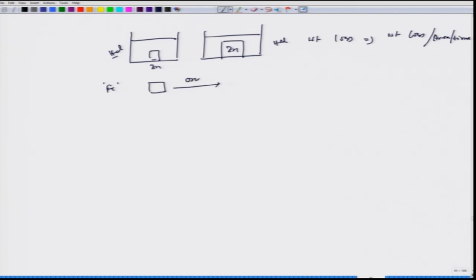some 1 month you have exposed it, and then you measure the weight, and that time you also spray a little bit of NaCl solution, you would see that the weight loss is not there, rather there is a weight gain. So now we are confused, but actually there is no point in getting confused, rather there is also corrosion.